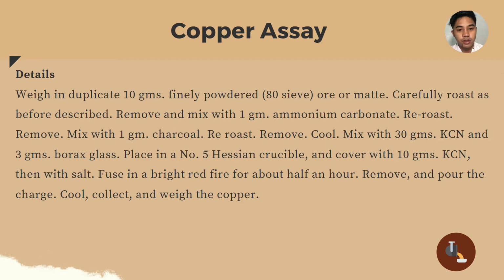In weighing the details for copper assay, weigh in duplicate 10 gms finely powdered ore or matte, and carefully roast as before described. Remove and mix with 1 gm of ammonium carbonate, then re-roast, remove, mix with 1 gm charcoal, re-roast, then remove again, cool, mix with 30 grams KCN and 3 grams borax glass, place in a number 5 Hessian crucible, and cover with 10 gms KCN with salt. Fuse in a bright red fire for about half an hour. Remove and pour the charge, and collect and weigh the copper.